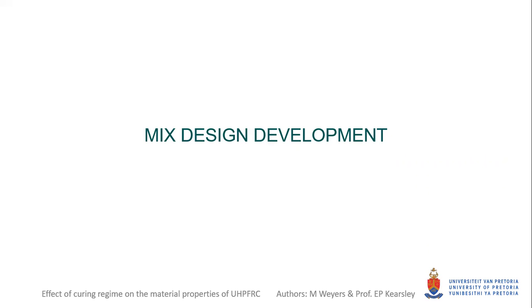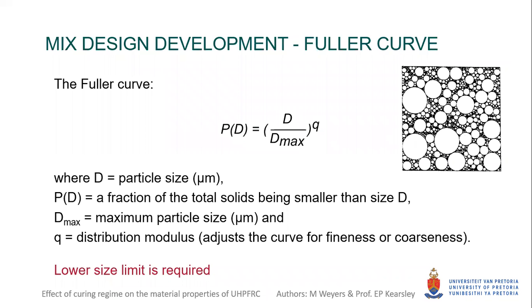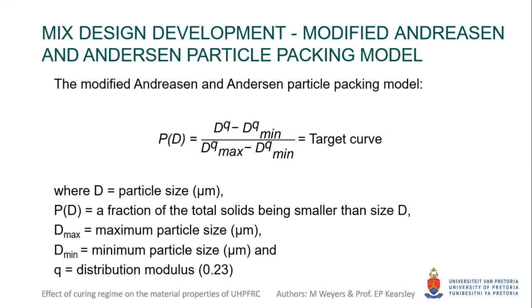The concrete mixture design development in this study was based off of particle packing model theory. Looking at the equation used to calculate the well-known Fuller curve, this equation only considers maximum particle size, and it is recommended that a finite lower size limit is required to better represent the finer particles. It was therefore decided to use the modified Andreasen and Andersen particle packing model to optimize the ultra-high performance concrete matrix. This method incorporates minimum particle size, and the range of fine particles is better represented.